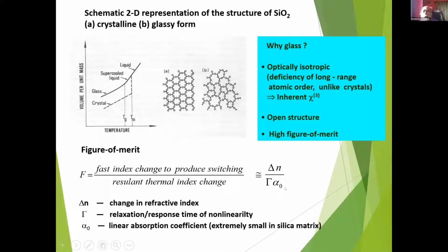This is the linear part, the extinction coefficient or absorption coefficient, and tau is the relaxation or response time of nonlinearity. So for the glasses, this tau is smaller and alpha 0 is also very small. So for the glasses, we are having a very high figure of merit.